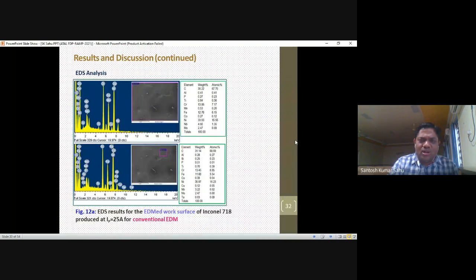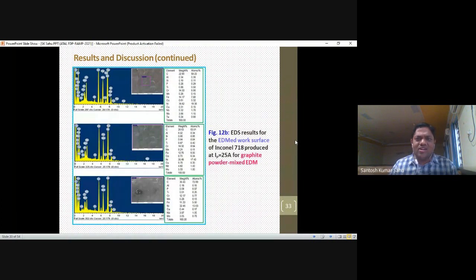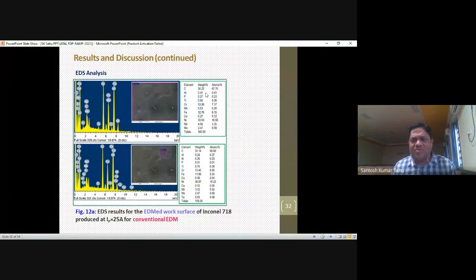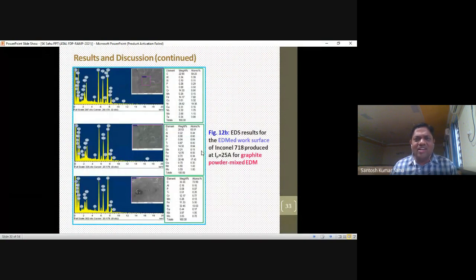By viewing the two graphs in the EDS analysis, we can conclude that on the right side you see many compositions available, carbon, aluminum, and others, and we can see the significance. One is that carbon is significantly very high during powder mixed EDM. From the EDS analysis, it was observed that compared to the received Inconel 718, the EDM'd surface obtained through conventional EDM as well as powder mixed EDM both exhibit relatively high carbon content. This is basically a consequence of the dielectric cracking, also known as pyrolysis of the dielectric fluid, which promotes carbon migration to the machined surface.